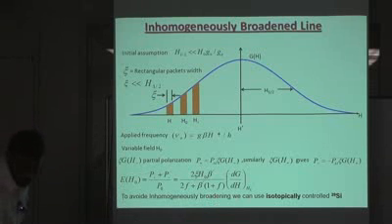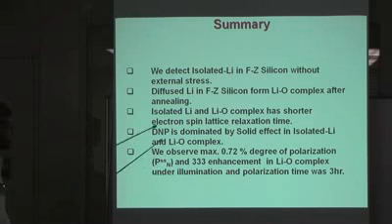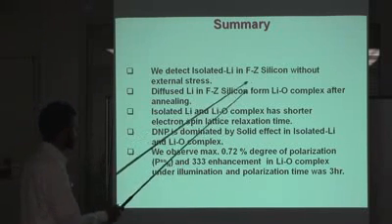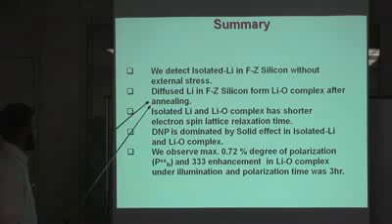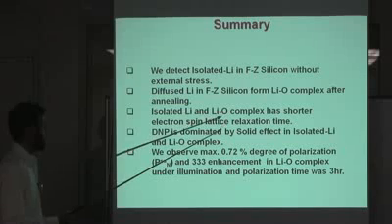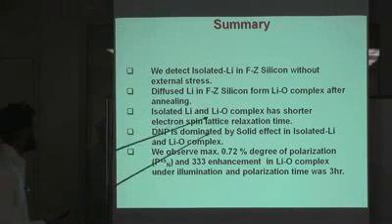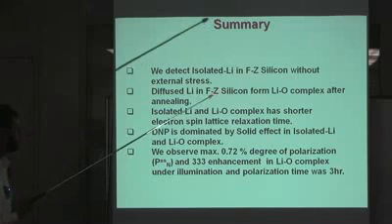Now I want to conclude my talk. We detected isolated lithium in floating zone silicon without external stress. Diffused lithium in floating zone silicon forms the lithium oxygen complex.